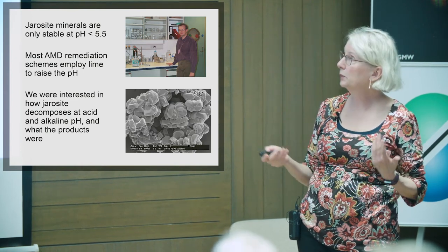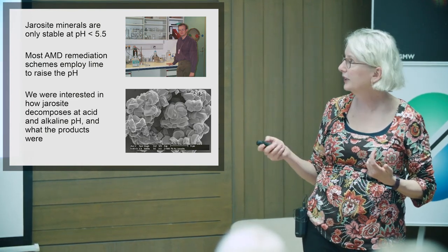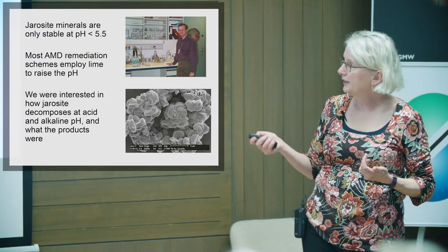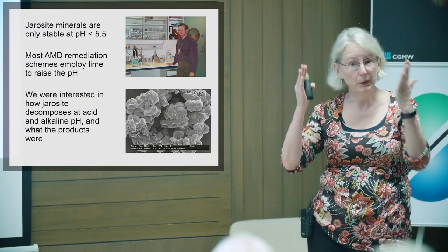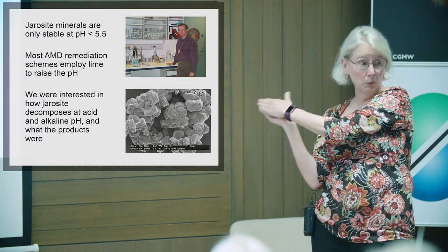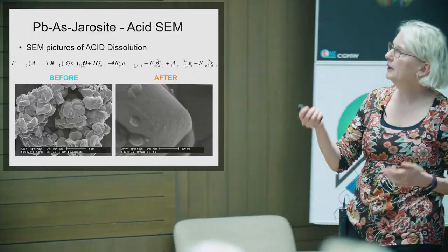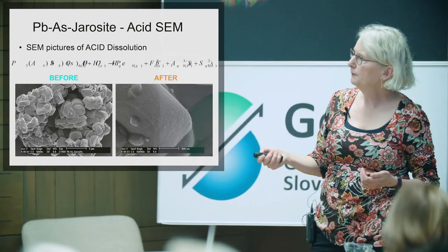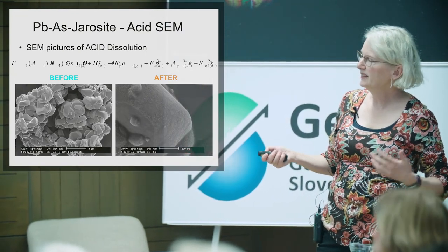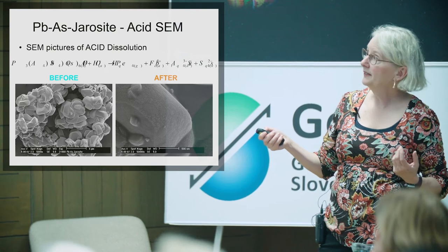So Adrian also worked in the lab. He loved making jarosites. So he made lots of jarosites, and then he dissolved them, both in acid water and in lime water, so high pH. So here's some of his results. He made a lead arsenic jarosite. Here's before, and here's after. You can see it's all being eaten up with acid dissolution.